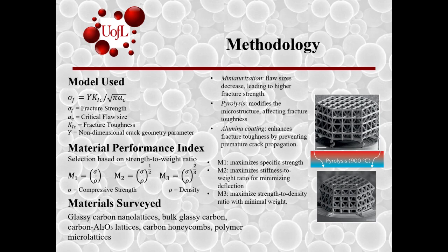glassy carbon through pyrolysis. Pyrolysis basically involves heating the polymeric structures in a vacuum at 900 degrees Celsius, causing them to shrink isotropically to about 20% of their original size to then form dense glassy carbon with improved mechanical properties. Some structures were coated with a 10 nanometer thin layer of alumina, which was used to enhance buckling resistance. The material indices used include M1, M2, and M3, where sigma is the compressive strength and rho is density, to identify the materials with optimal strength to density ratios.